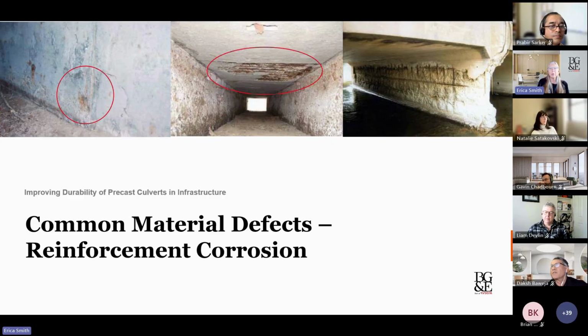So it may appear just as rust stains, as you can see on the left-hand photo here. But then the expansive nature of the advanced corrosion to the reinforcement is in the order of 4 to 6 times its original size. So what happens is you then get cracking, delamination, and ultimately spalling off of that concrete, and then you get heavily corroded reinforcement that's no longer protected from the environment. These are some photos here of culverts throughout the state, predominantly in the wheatbelt in WA.